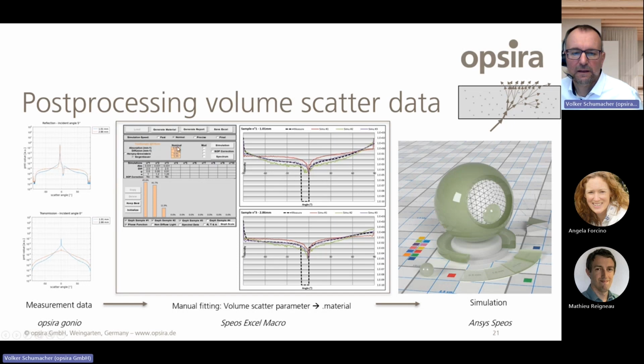And when we have a set of parameters, we can start a simulation in Speos, and this simulation delivers back some fault values, and also some results of the simulation, and this can be compared with the measurement data. We see here the dotted black line is the measurement data, and the red line is the first set of data. The green line is the second set of data. And the purple line, this one here, has a very good fit to the measured data. This is the third set of data.